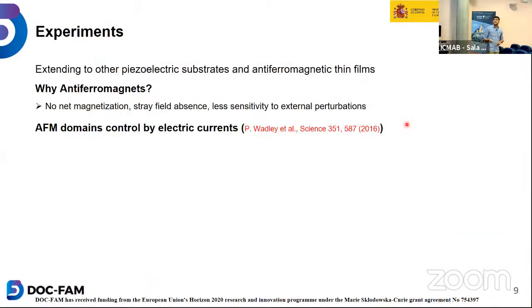So now we are extending our experiments to different piezoelectric substrates, because previously we have been using lithium niobate, with different antiferromagnetic thin films. But why antiferromagnets? Because they don't have net magnetization, since their magnetic moments are opposite and cancel. The stray fields are absent. So when you apply a magnetic field, they react, but you have to overcome the magnetic field force, and they are less sensitive to external perturbation.